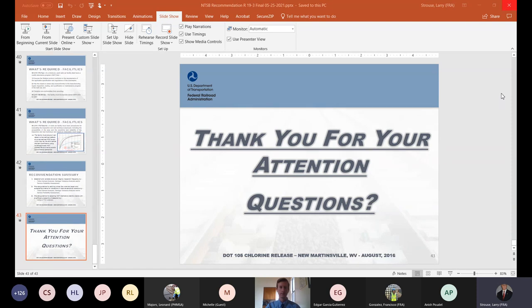185.11 says that the tank qualification activity must find defects that will initiate or propagate cracks to failure of the tank. So the only way to do that is by performance demonstration of the technicians who perform that work. So does that mean that subcontractor personnel would need to prove that as well? The answer to that is yes. So if you're getting a third party subcontractor in who's performing UT or penetrant, you would need to have some samples on hand that prove to you that they can detect the flaws that the owner is interested in detecting at a particular level of POD.